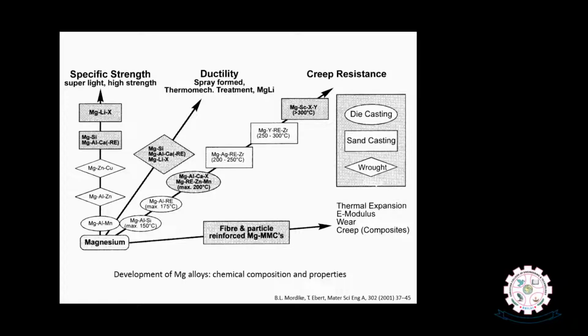And we'll see the role of different alloying elements, the influence of the chemical composition on the bulk properties of the developed alloys and composites, how different alloys contribute. For example, addition of lithium, and addition of zinc and aluminum and manganese and copper will give those kinds of alloys excellent specific strength at light weight, the ability to bear higher amounts of loads. Whereas when we add elements like rare earths, like silicon, yttrium, such elements, when we add to magnesium, the magnesium alloys developed from these elements will give better creep resistance.